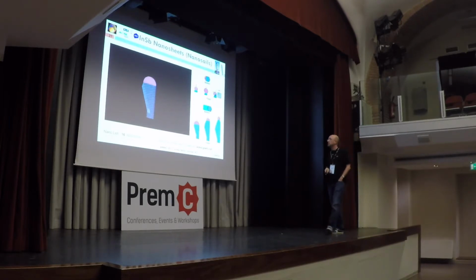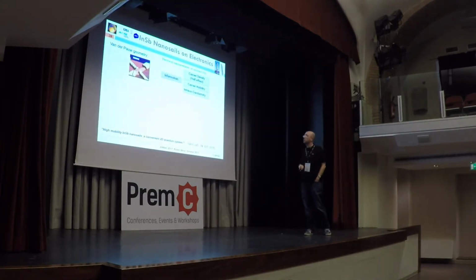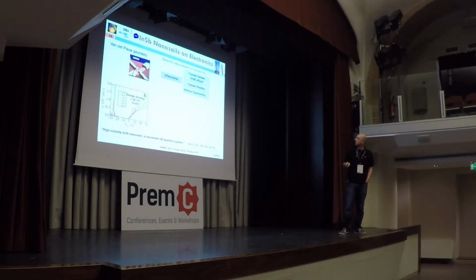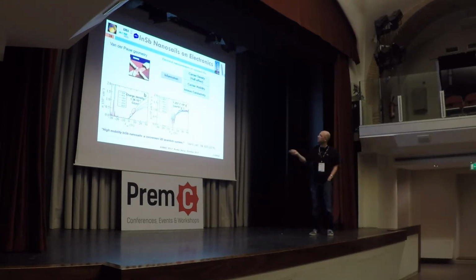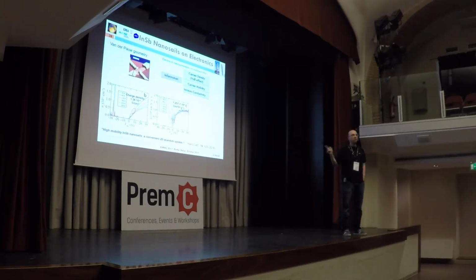So you can tell me, is that interesting for electronic applications and quantum applications? Yes, it is. If you check, for example, the mobility of this material, you will see that maybe it's not as good as the bulk material, because it's 7 times lower than the bulk material, but I can tell you that it's 4 times higher than any other thin film with exactly the same thickness. So if you check the literature, the mobility of this material is 4 times higher than any other thin film of 70 nanometers, like it is in this case.